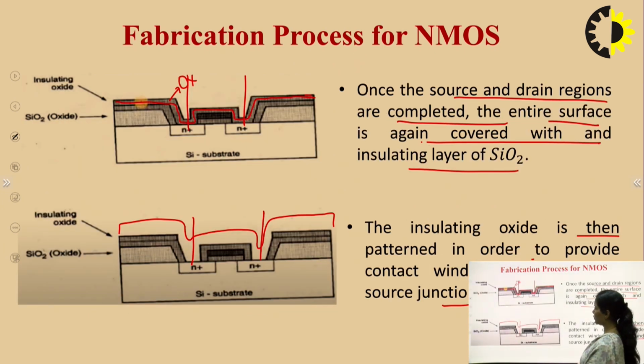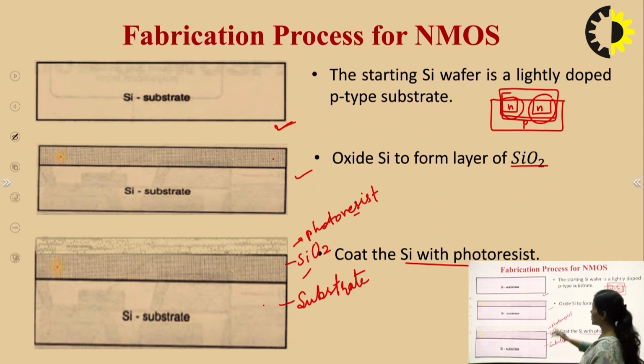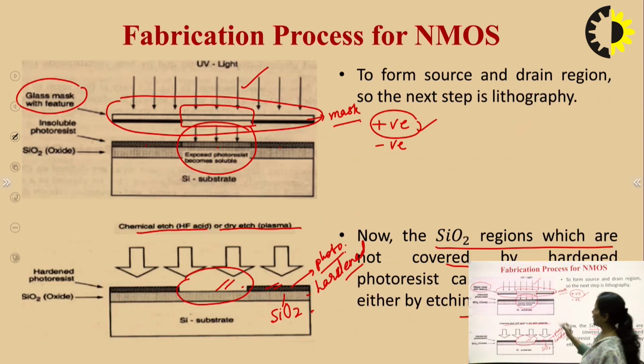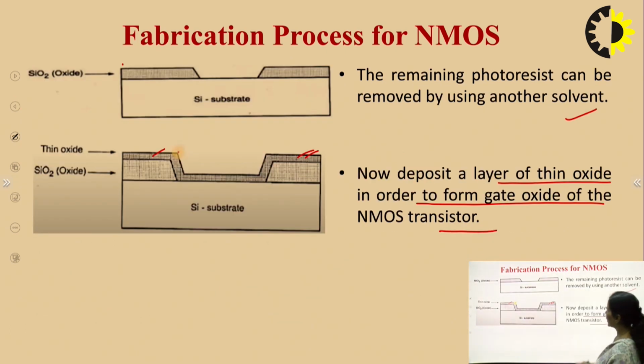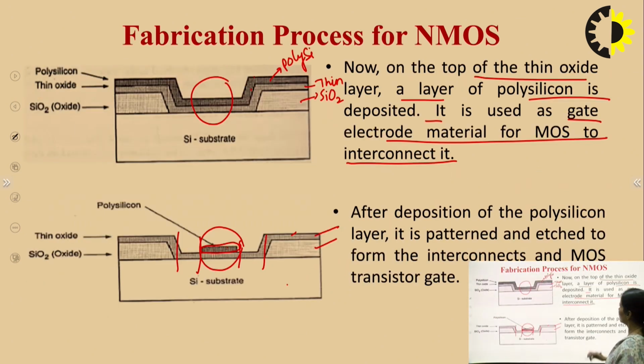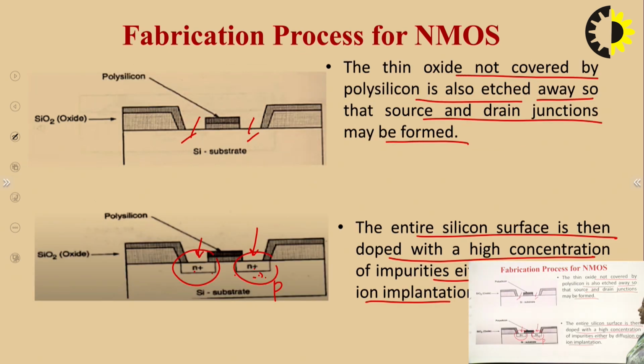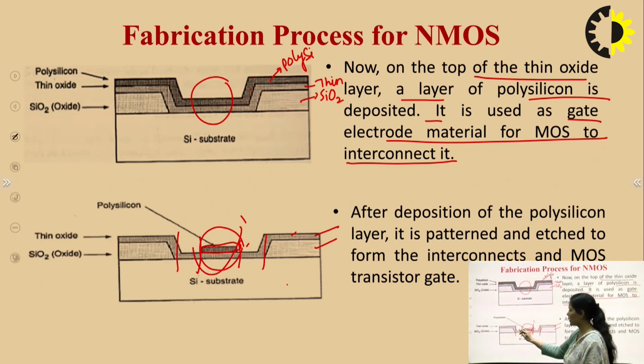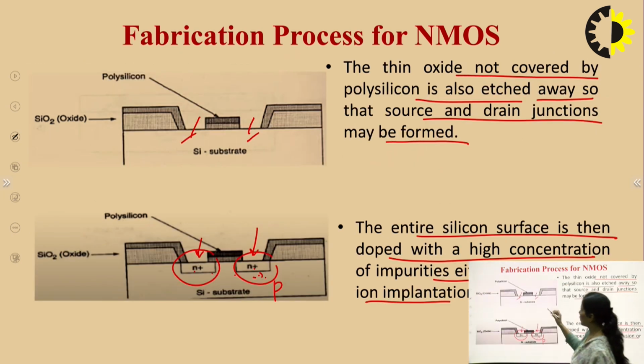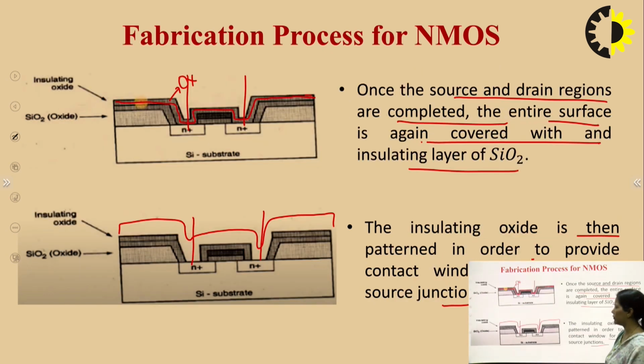Let us again give a quick recap. Starting from the substrate, first of all the oxide layer was grown, and then the polysilicon layer was deposited. Then it was patterned to make the openings for source, drain and the gate regions. Now again the etching was done and the thin oxide layer was grown. On the thin oxide layer, again the polysilicon layer was grown to make the interconnections, and then it was used to form the gate. So to make the gates, the oxide layer from the other regions is also removed.